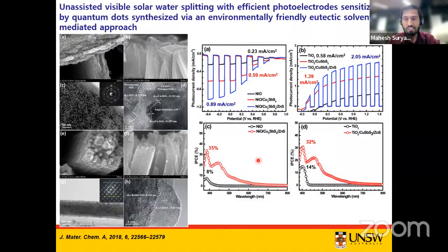Of course, we'll explain a little bit about the IPCE. So from IPCE, you can see that after sensitizing with these copper chalcogenide compounds, let's say copper antimony sulfide, Cu3SbS4 and CuSbS2 on NiO and TiO2, there is an improvement in the visible light activity of the NiO and visible light activity improvement of the TiO2. That simply suggests that these compounds act as visible light absorbing compounds to improve the visible light absorption capability of the NiO and the TiO2.